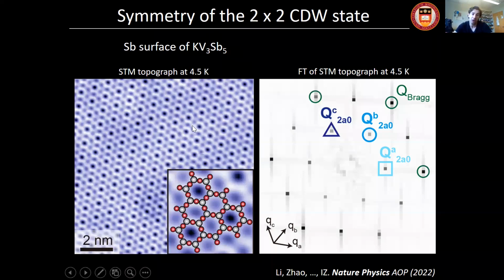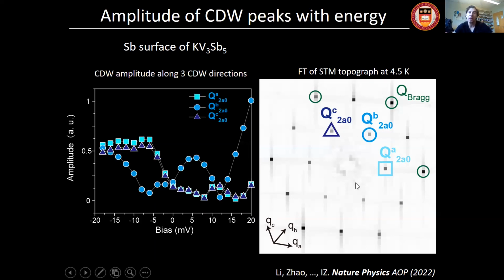So this is the topography. On the right is the Fourier transform of the topography, where you can again see this 2x2 charge density wave state denoted by these three symbols. We drift correct our images that I show here, so that's why they're single pixel, and they're nice. It's easier to compare the intensities across different data sets. I can answer more there, but that's why they're single pixel here, and they're actually quite sharp.